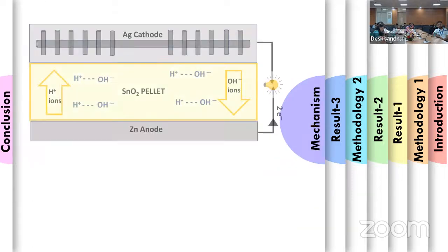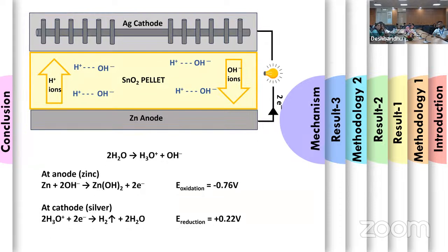Now to understand the mechanism of the hydroelectric cell: first, tin oxide has low defect formation energy and unsaturated surface cations. So what happens? Firstly, dissociation of the water molecule takes place on the tin oxide surface. As the water gets adsorbed on the surface, it gets dissociated and forms an SnOH layer. On this SnOH layer, due to hydrogen bonding, further multilayer adsorption of water molecules takes place.